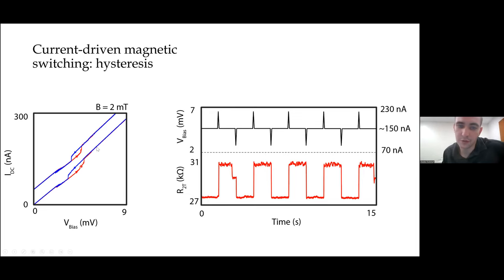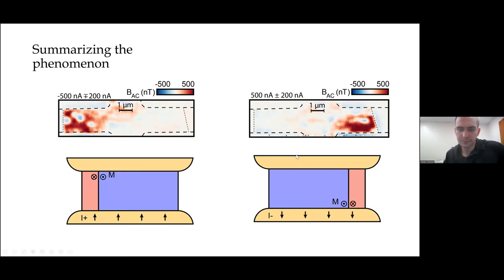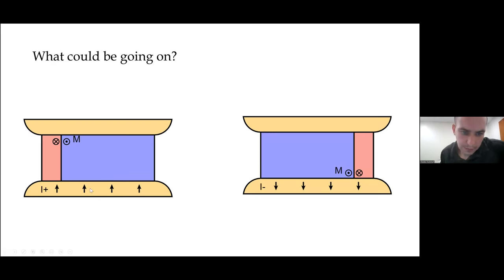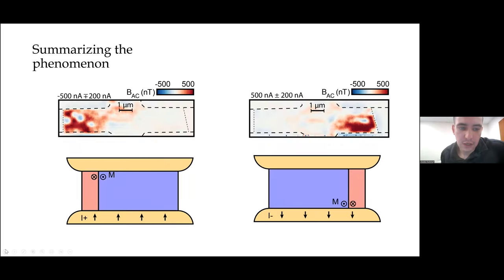So a hysteresis loop is shown on left, and then flipping of the bit as a function of time is shown on the right. So just to summarize the phenomenon, as we flow current from bottom to top of the device, we have this magnetic domain that's stabilized on one side transverse to the flow of current. As we flow current in the opposite direction, we have a magnetic domain stabilized on the opposite transverse side.